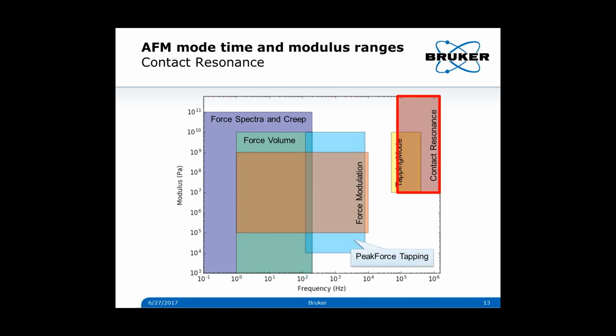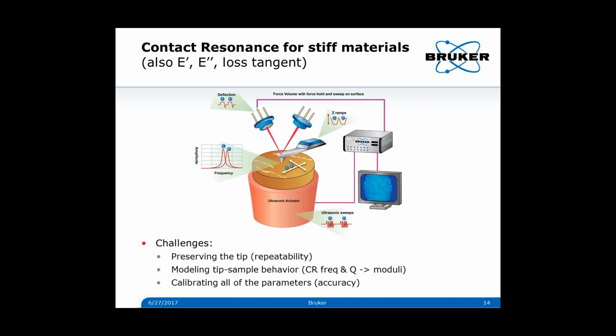Okay, so moving on, I'd like to also spend a few minutes talking about contact resonance, as Dalia did. This is our resonance technique that is really great for high frequencies and stiffer materials. This is how it works. Essentially, we ramp Z, and we have a couple of different pixels here, A and B, and we control the force during that process. While we're at each of the different loaded pixels, we send a little ultrasonic sweep through an actuator, and we look at what the resonant frequency is of the tip during that process.